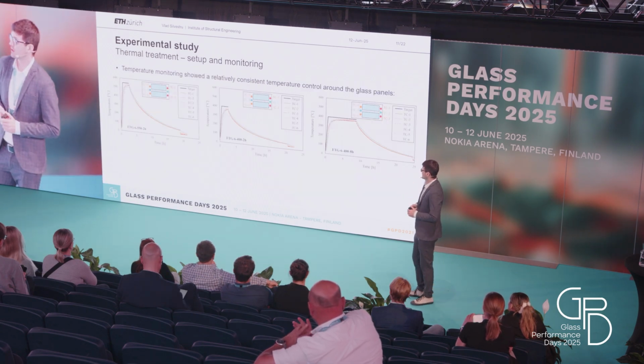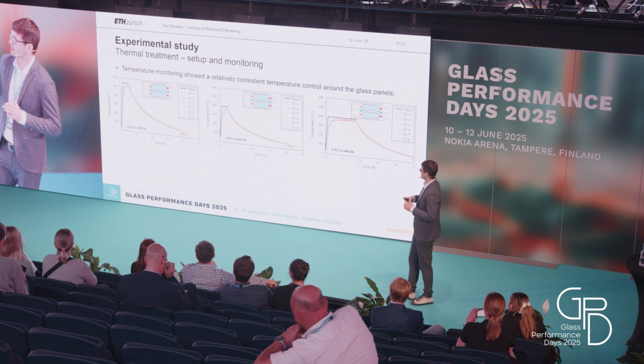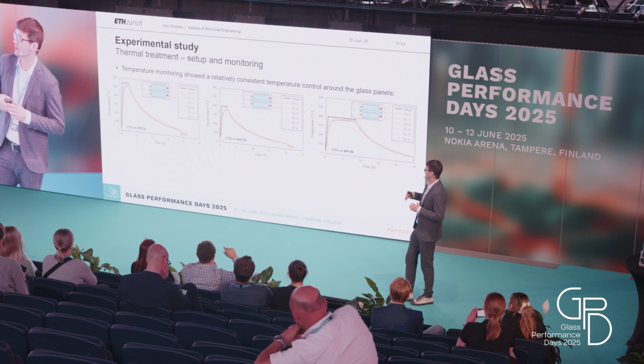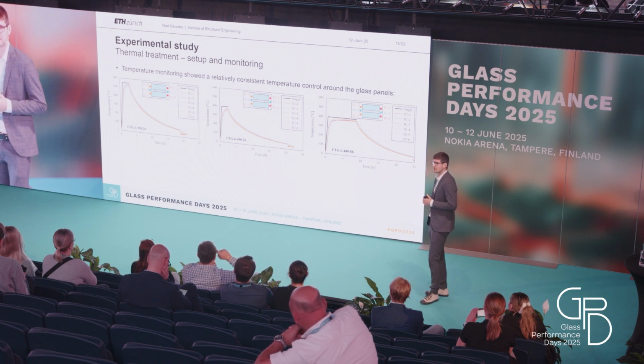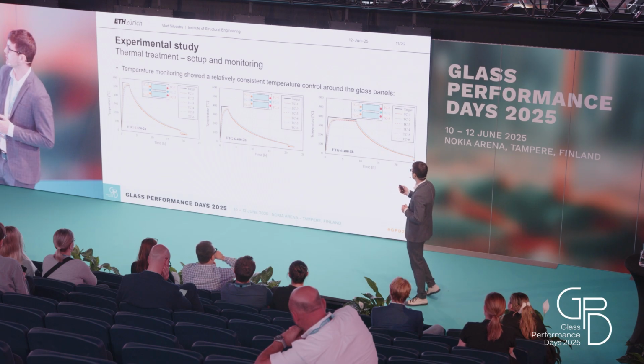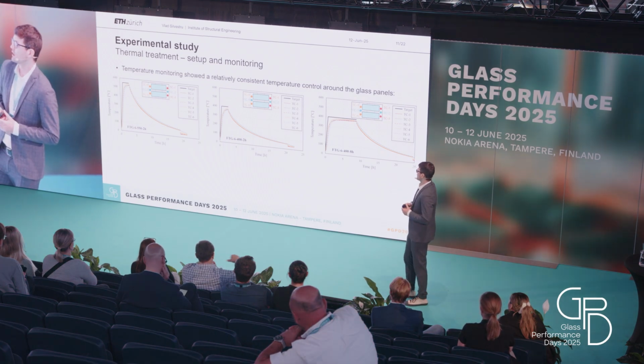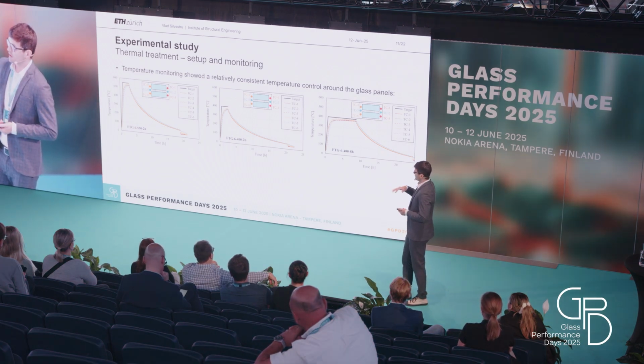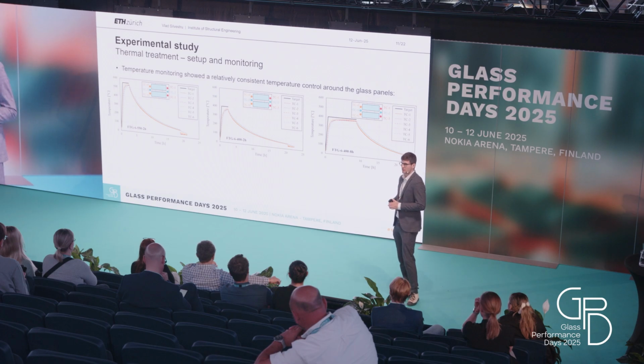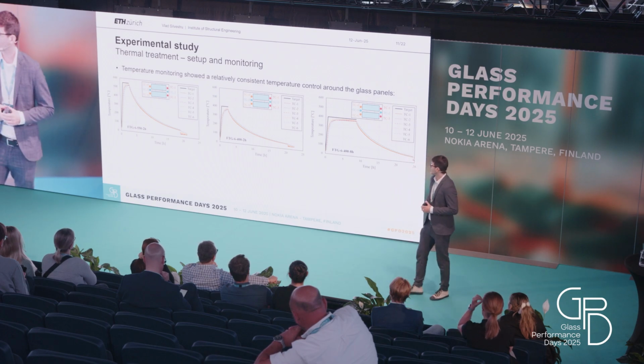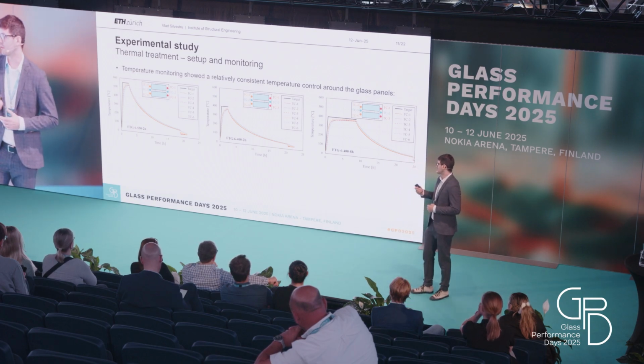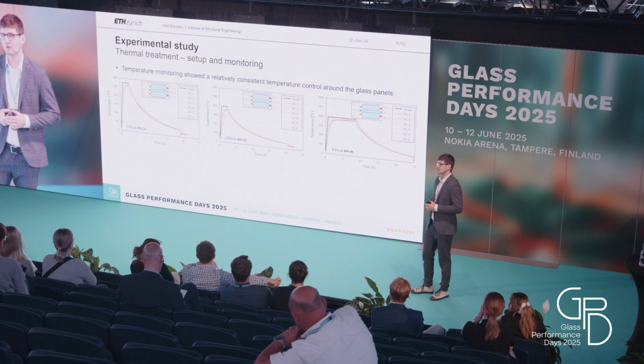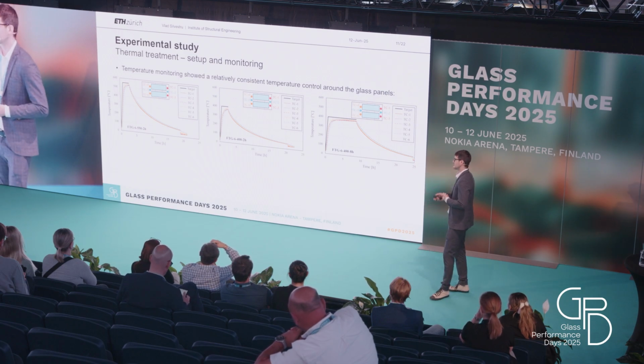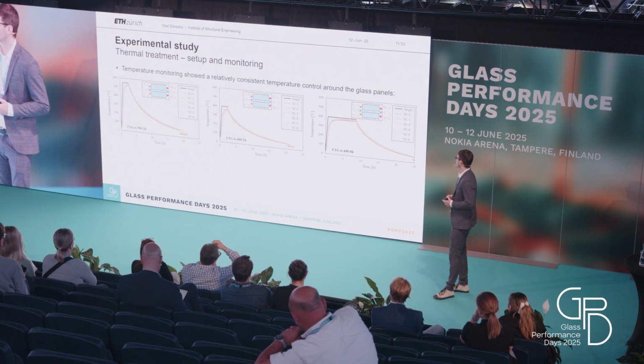And you can see here that actually the temperatures around the glass panels lagged a little bit behind the target temperature, which is the black curve in these graphs. So for the heating, I had a speed of 10 degrees per minute. For the cooling, the furnace did not have a cooling function, so I just left the glass panels overnight to cool naturally in the furnace, and the next day I took them out.